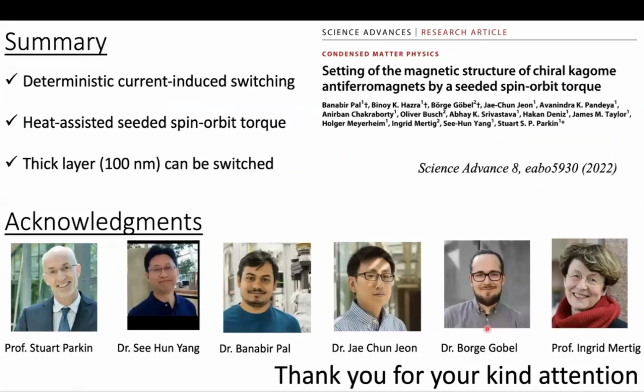And we could switch a 100 nanometer thick layer. That is beyond the spin diffusion length of manganese 3 tin. Typically the spin diffusion length is 1 or 2 nanometers in the case of manganese 3 tin. So that can't be explained using the standard spin orbit torque model, whereas our seeded spin orbit torque can explain our result quite well.